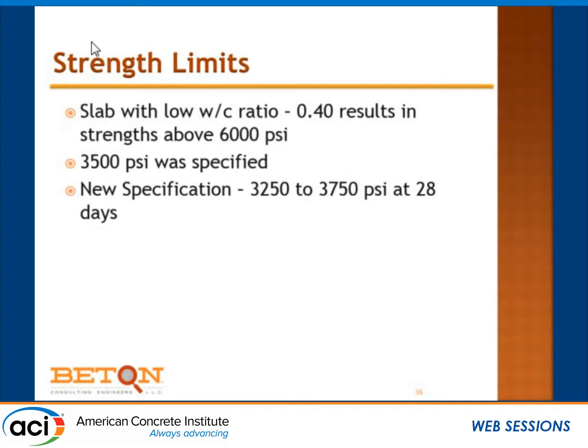So they execute the next several projects, and the stores all have curling all over the place. And they come back and say, I specified 3,500 PSI, and your concrete's all coming in well over 6,000. So, well, yes, but you specified a 0.40 water cement ratio, and that's what we do. And if we go back to the table in 211, we're getting the same predictability. We're at 6,000 PSI. So they changed their specification, and it came out and said, we want the concrete compressive strength to be between 3,250 and 3,750 PSI at 28 days.